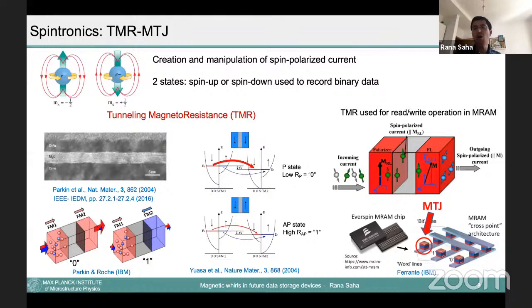Now the question is how you can write. You can pass a higher current. Suppose you are passing a higher current through this structure. What happens? As I mentioned, when it goes through a ferromagnetic layer, the spins become polarized, meaning the incoming electron will follow the magnetization of this layer. So the up spin then enters this ferromagnetic layer. This ferromagnetic layer on the left side is a fixed ferromagnet, the magnetization cannot switch. On your right side, this layer can flip its direction.